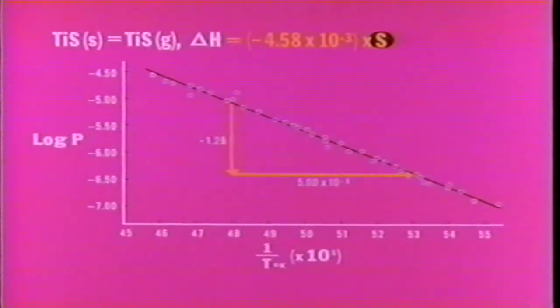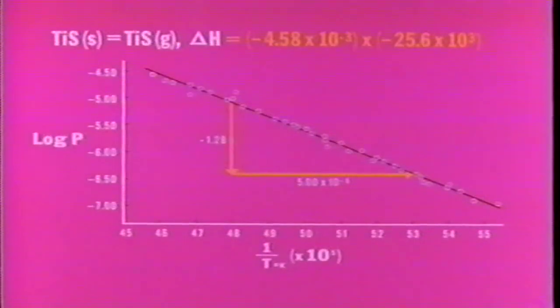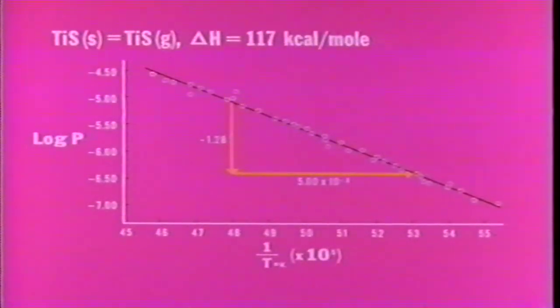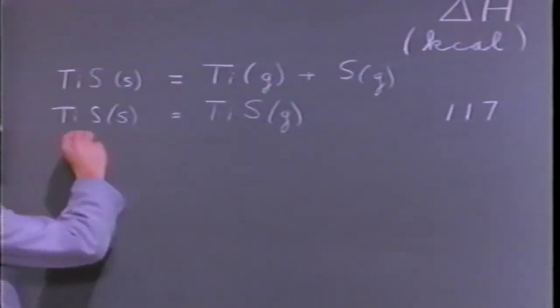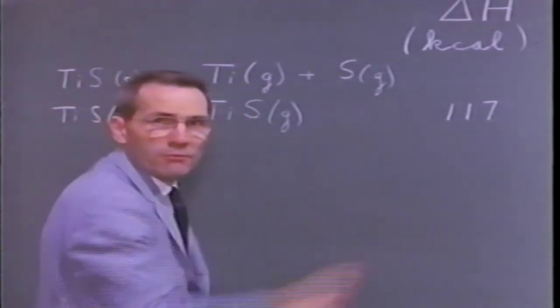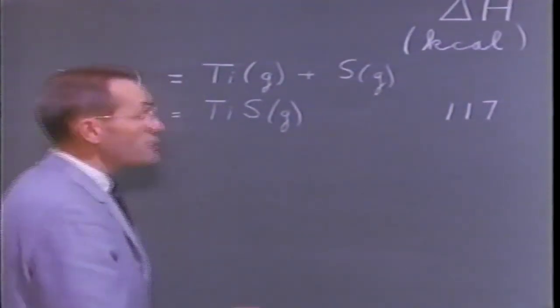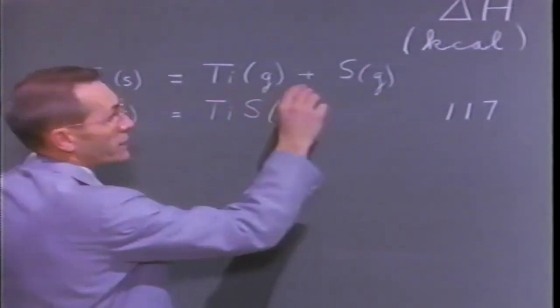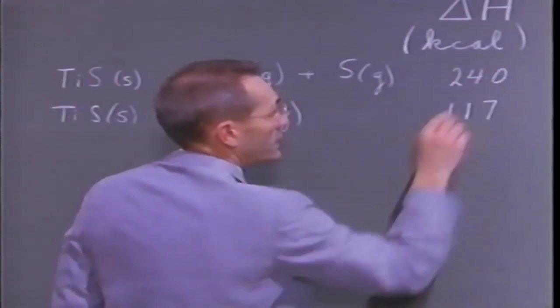The slope of a curve is defined by the ratio of its vertical component to its horizontal component, or the slope is equal to minus 1.28 over plus 5 times 10 to the minus fifth, or minus 25.6 times 10 to the third. The heat of reaction is 117 kilocalories. Thus, delta H for this reaction is 117 kilocalories. Similarly, we find that delta H for this reaction is 240 kilocalories.